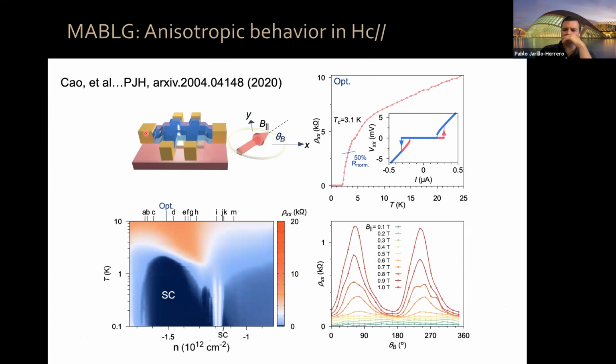So we take magic angle graphene. We measure at zero magnetic field. It exhibits superconductivity, a pretty high critical temperature for this device, sharp voltage-current characteristics, etc. And then here is the superconducting dome in log scale as a function of density. This is, by the way, one of those devices where we see a competition in orders, depletion of TC at a certain doping.